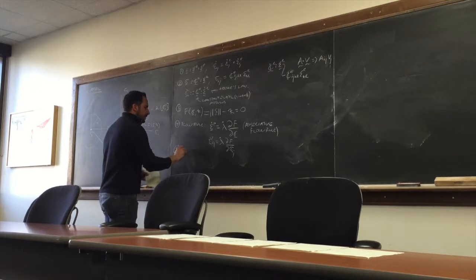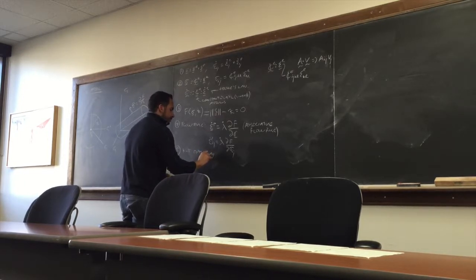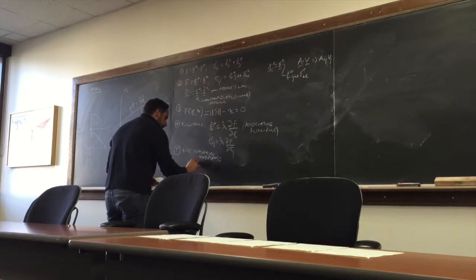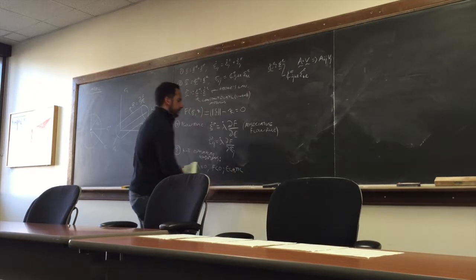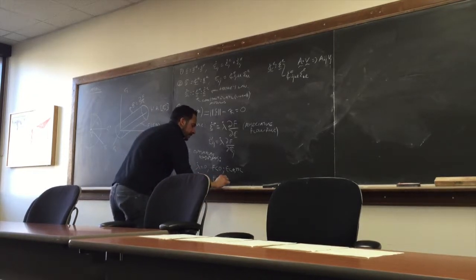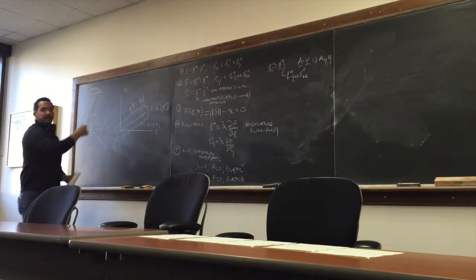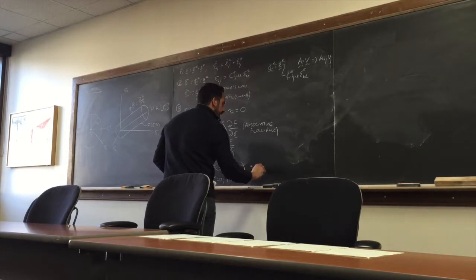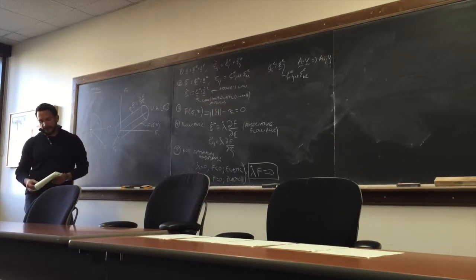Fifth, your KT or Kuhn-Tucker optimality conditions. Remember, there are 3 of them, right? The first, well, really 2, and that boils down to the third. Lambda dot equals 0, F less than 0 if the process is elastic, right? Lambda dot greater than 0, F equals 0 if the process is plastic, or if you are on the yield surface, right? That's a plastic process. And from this, you can essentially generalize that lambda dot F is always 0. Right? That's your optimality condition, essentially. Always.